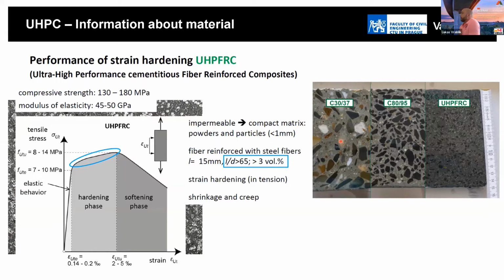I think a very nice comparison is these three pictures, three grades of the concrete: normal concrete C30/37, then high strength concrete C80/95, and UHPC. If you compare the density, or the volume of the concrete, you can see the aggregate. Also, you can see the volume of the cement between the aggregate. In UHPC, the volume is completely closed. There are no hollows, no bubbles, completely closed material.